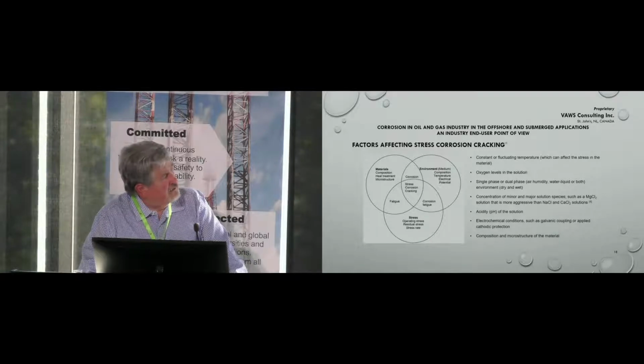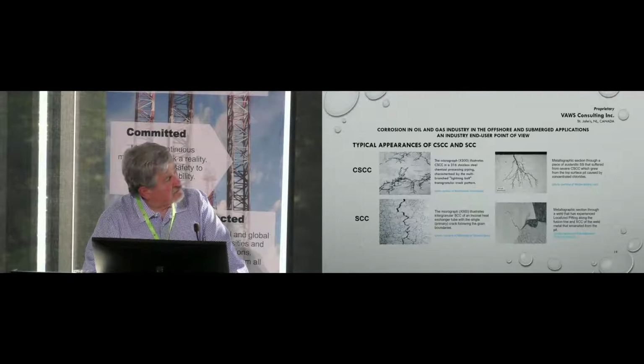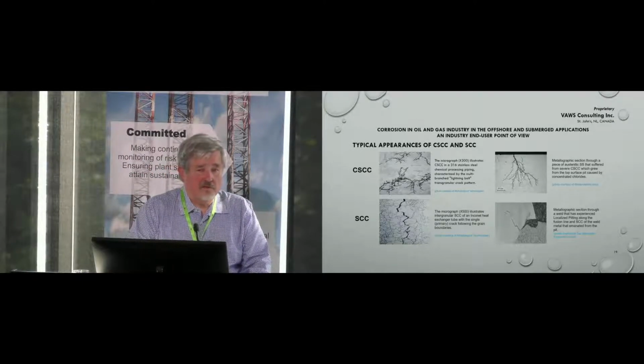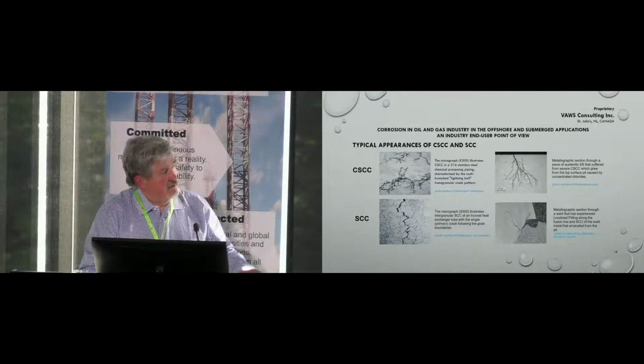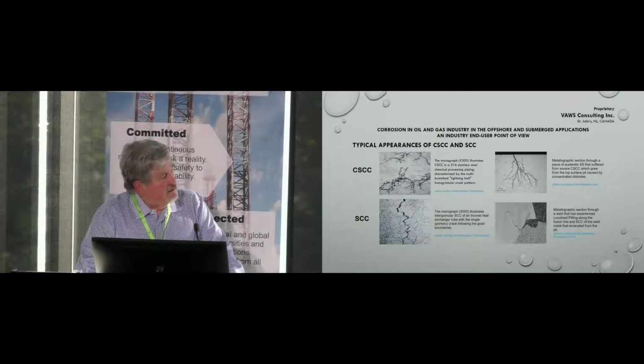Chlorides affect stress corrosion cracking. If you have chlorides in the water, or if you have pockets of water which have high chlorides, you can reach conditions where you have stress corrosion cracking, which is in the middle of these balloons. You can differentiate between chloride stress corrosion cracking, which is the top two figures, and sulfide stress corrosion cracking. The chloride stress corrosion cracking looks like flames coming down through the metal. They always start with a pit on the surface where the chlorides are the highest and progress in sort of a tree-like fashion into the metal.